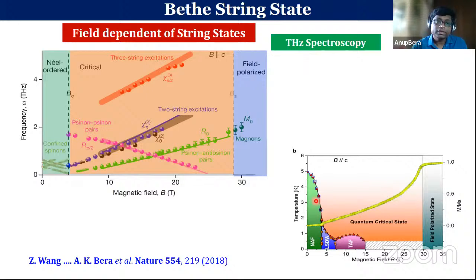Further, we continue to look at how this string state varies up to the saturation magnetic field by terahertz spectroscopy, which comes around 28 Tesla. Now we see these 2-string and 3-string states disappear at high field, and rather the low energy excitations become magnons when it saturates, which is expected for a ferromagnet.